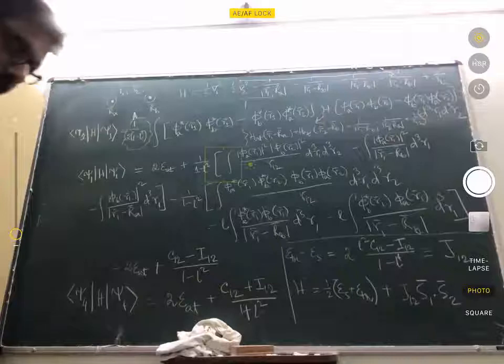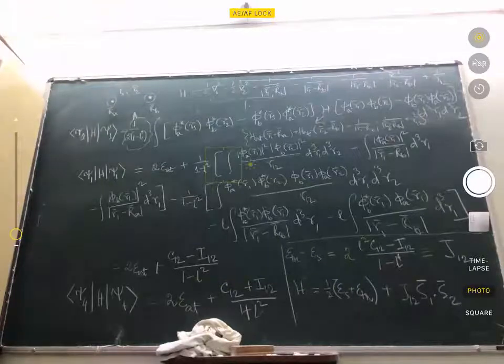So we have generated an effective spin model in which the coupling can be tuned depending on the distance between these two atoms. This is the part that was missing last time. The direct exchange between orthogonal orbitals that we discussed earlier always gives you a ferromagnetic coupling, but there are antiferromagnetic materials in which successive spins are oriented opposite to each other.